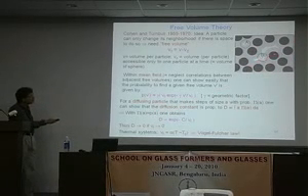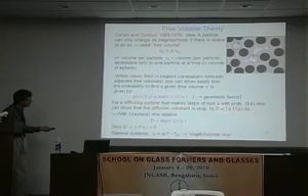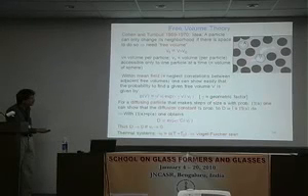And now, if you say that here I have free volume, and as soon as the free volume has a certain range I can go, I'm diffusing, you plug this distribution into this expression, and you get out that the diffusion constant is related to the exponential of minus C over Vf. So you see that if Vf goes to 0, so the amount of free volume goes to 0, the diffusion constant goes to 0, and therefore you are getting stuck.